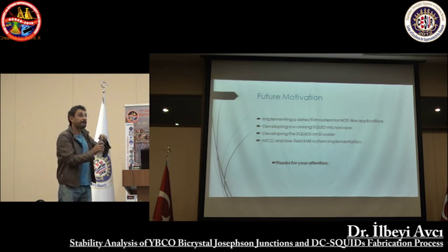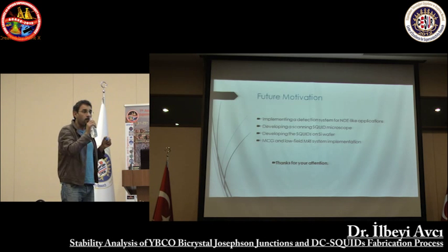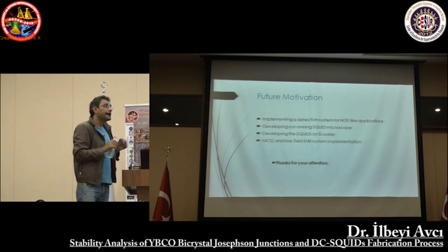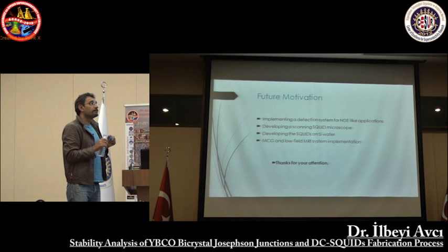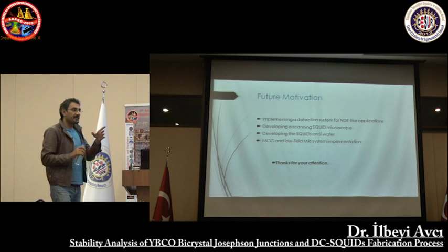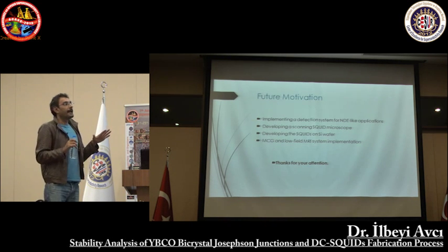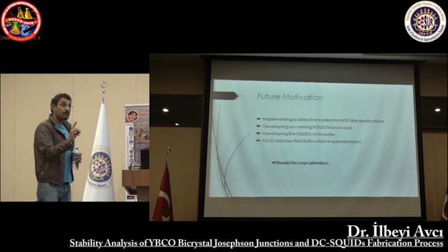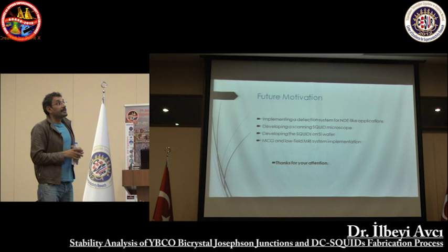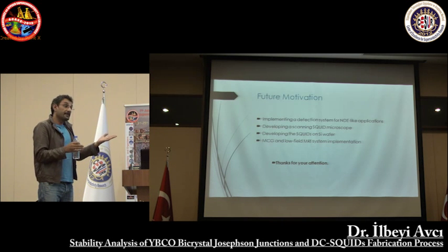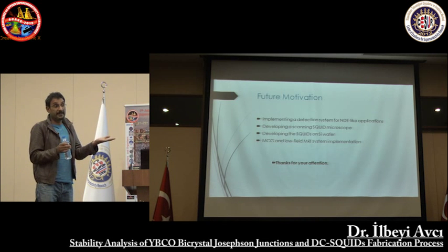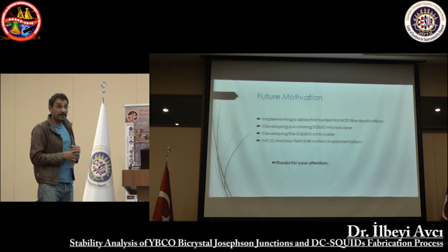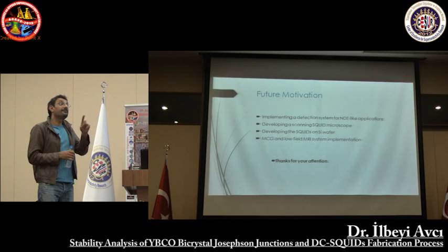Is 1 nanometer per minute the lowest growth rate that you have studied, and is there a reason why that should be the limit? Isn't that too high? Well, that's our limit. As I mentioned in the beginning, there are no standard parameters for YBCO thin film fabrication. With PLD systems, for example, people are using 20 nanometers per minute. We have used 3 nanometers per minute, 5 nanometers per minute, even 0.5 nanometers per minute. But we got the best results with 1 nanometer per minute.